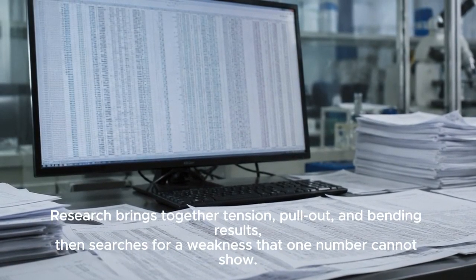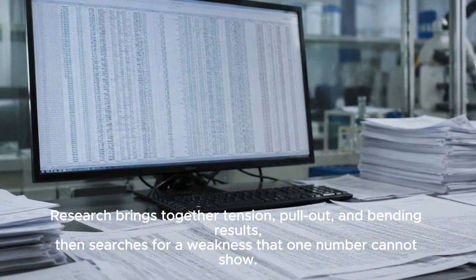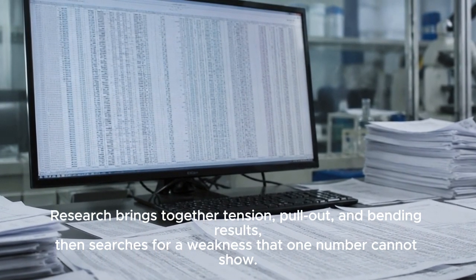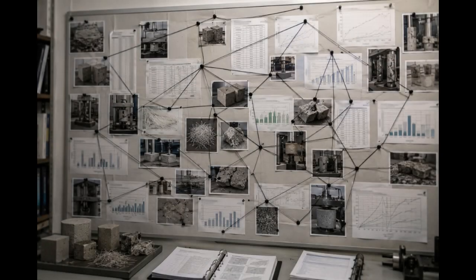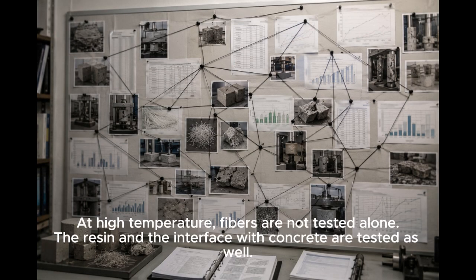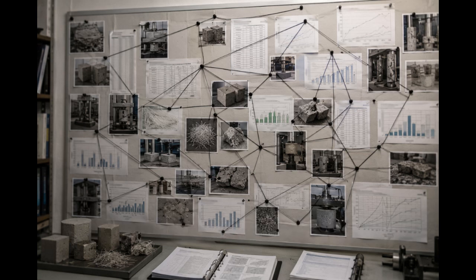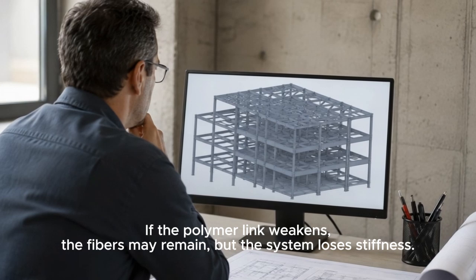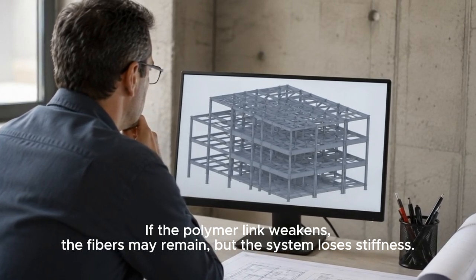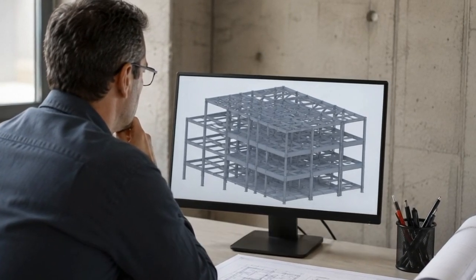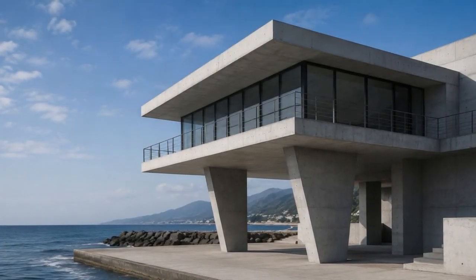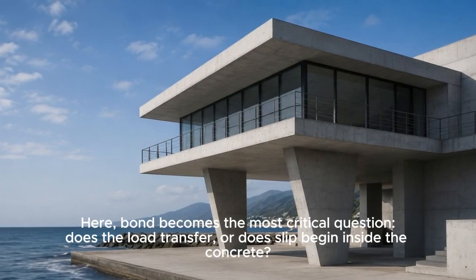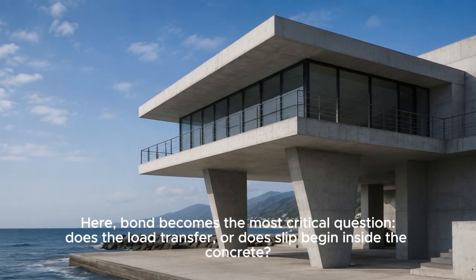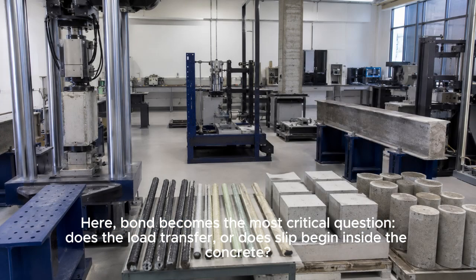Research brings together tension, pull-out, and bending results, then searches for a weakness that one number cannot show. At high temperature, fibers are not tested alone. The resin and the interface with concrete are tested as well. If the polymer link weakens, the fibers may remain, but the system loses stiffness. Here, bond becomes the most critical question. Does the load transfer, or does slip begin inside the concrete?